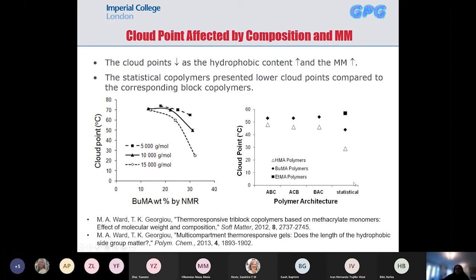In terms of how the architecture affects the cloud point, it doesn't affect it unless we don't have a block structure. So in all the cases where we have block polymers, in these three, each sample is a different chemistry of the hydrophobic group. So we're going from ethyl to butyl to hexyl methacrylate. But if you look at the same samples, the cloud points for the block-based structures are the same. The only one that is different is the statistical, the random copolymers. So the random copolymers cannot self-assemble to make micelles, like the block copolymers. So they're not as stable, so they have a lower cloud point. And that micelle structure is also important for the thermoresponsiveness, in terms of whether they're going to make a gel or not.